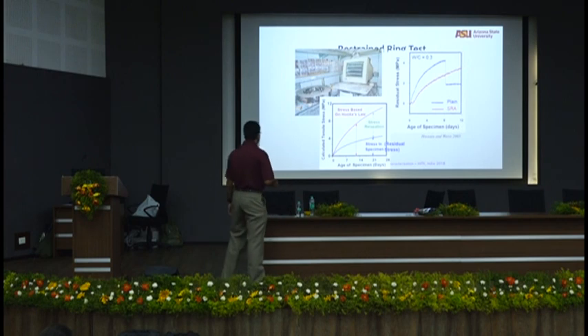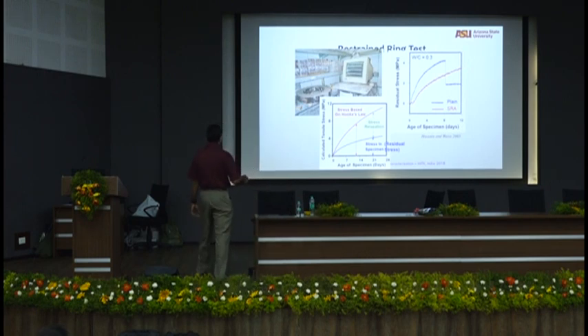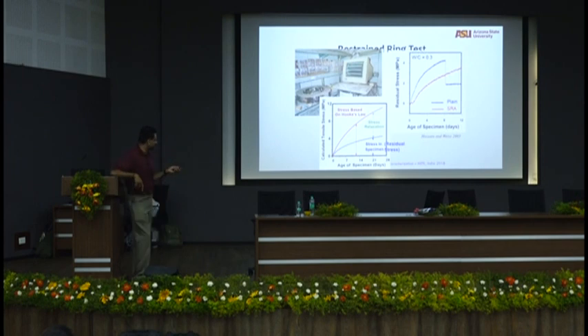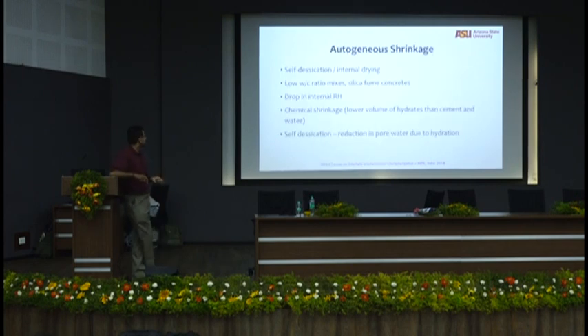The simplistic idea is you have a calculated tensile stress, specimen stress based on Hooke's law, stress relaxation. If you're doing a restraint ring test, the ASTM standard tells you how to do all of those. Autogenous shrinkage, self-desiccation, internal drying, low water cement ratio, we talked about that, drop in internal RH. Chemical shrinkage, lower volume of hydrates than cement and water. Self-desiccation is reduction of pore water due to hydration.